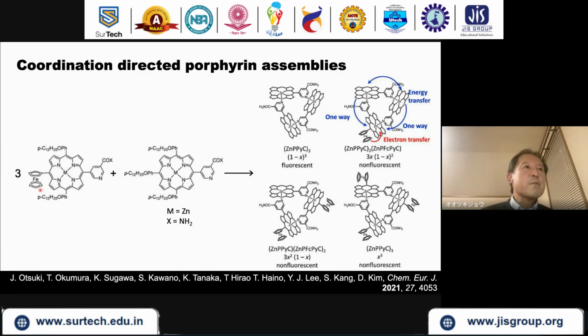And here's another version. We have put a tyrosine group here. Instead of fluorine, just opposite to the fluorine, tyrosine is a good electron donor. So upon excitation of the porphyrin sensitizer, electron transfer occurs from tyrosine to porphyrin. And so we have mixed these two. Oh, sorry, this is 1 and this is 3. And we mix these two, the one with tyrosine and without tyrosine. So we have these assemblies randomly containing various numbers of tyrosine groups. But let us focus on this one. This one has one tyrosine group, and the energy transfer happens around here, and electron transfer follows.